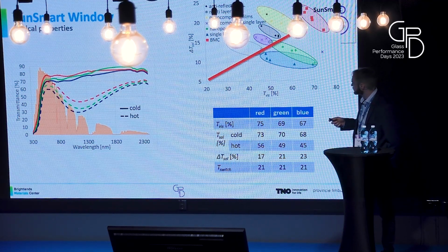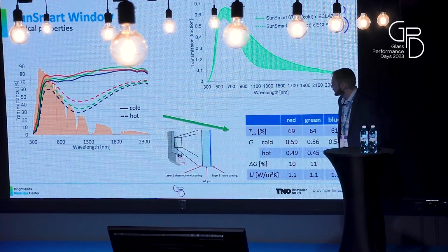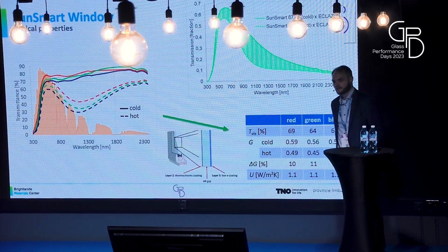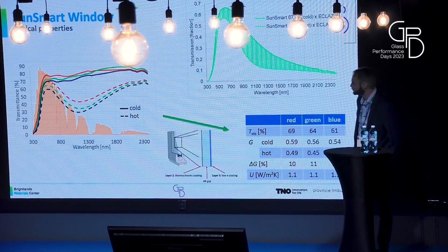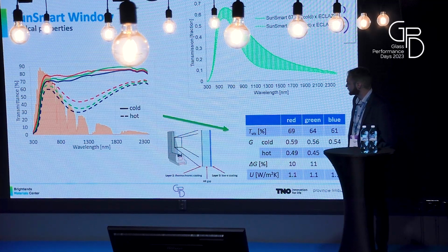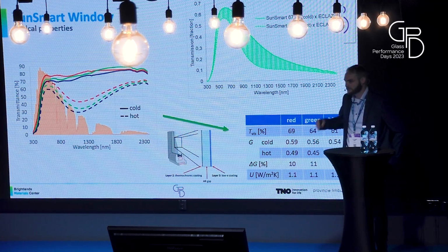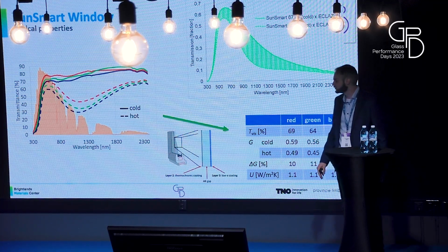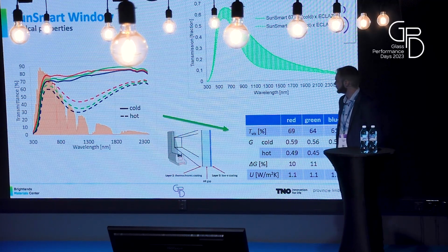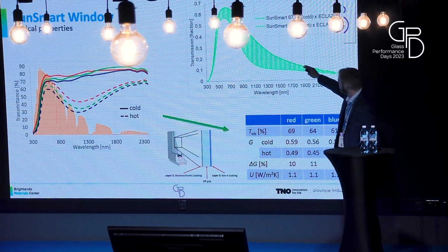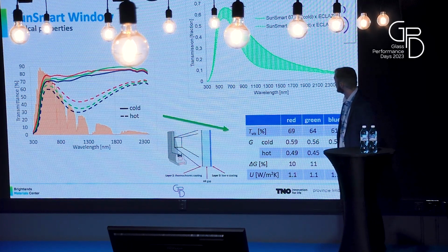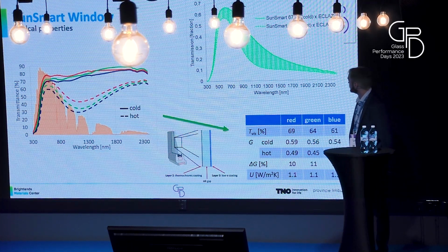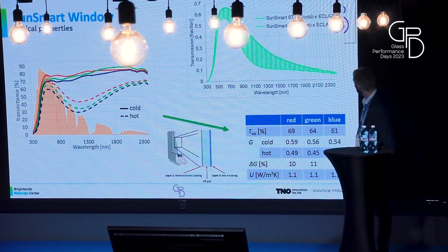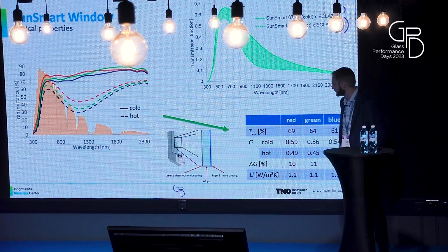But there are low E coatings on the market which are still very transparent in the region 800 to 1400 nanometers. And these are the type of low E coatings that you need to use to combine with the thermochromic coating to get to a perfect IGU. This is, for example, a spectrum of how it would look if you combine the thermochromic coating with a low E coated glass. This is in that case the ECLAZ series from Saint-Gobain.